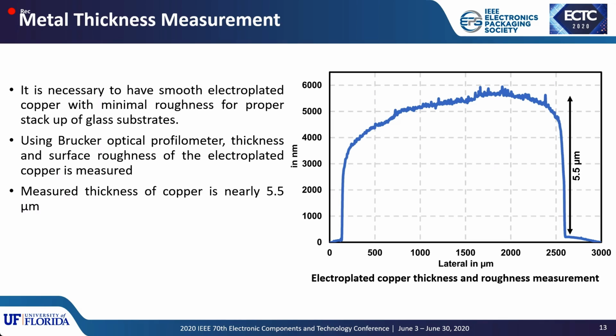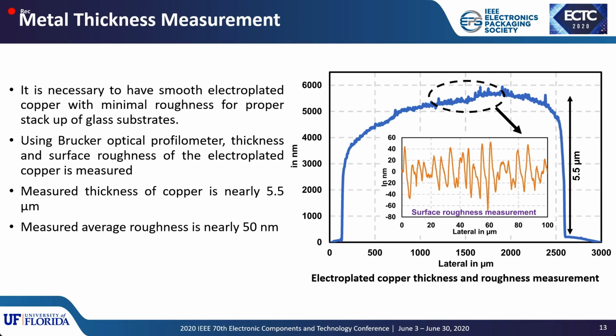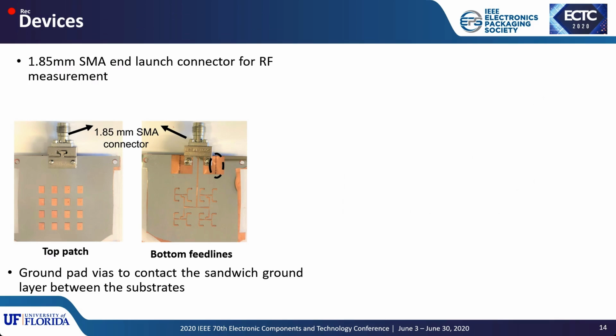The thickness of the metal deposited is close to 5.5 micron, and the surface roughness of this electroplated copper is measured using a Bruker optical profilometer, and the measured average roughness is close to 50 nanometers. So these are the two fabricated feed lines and the patches on the two glass substrates.